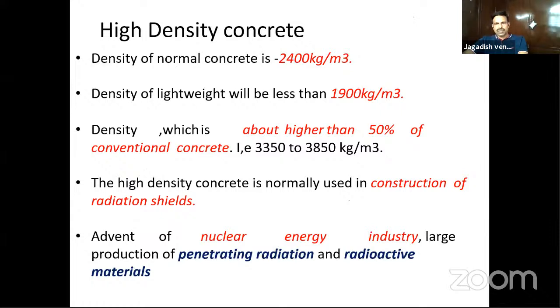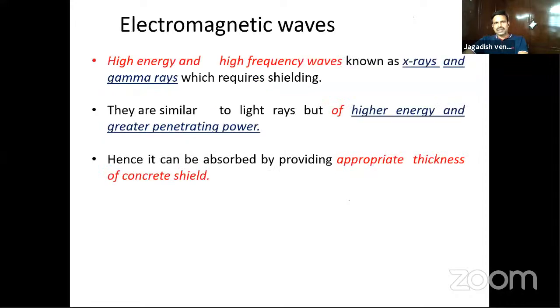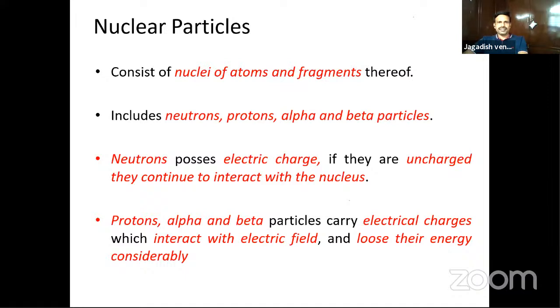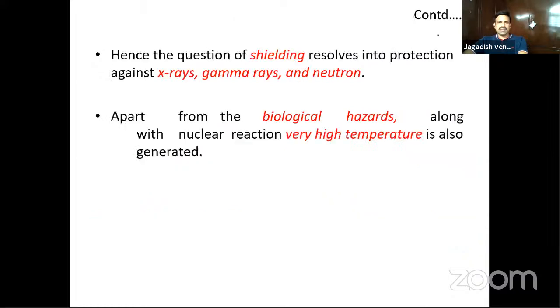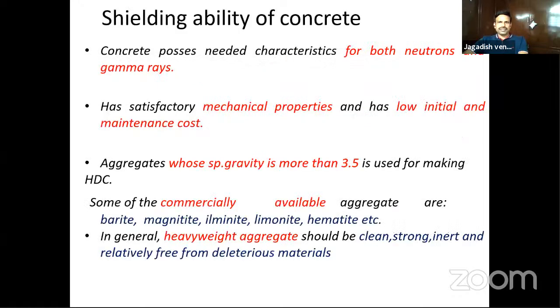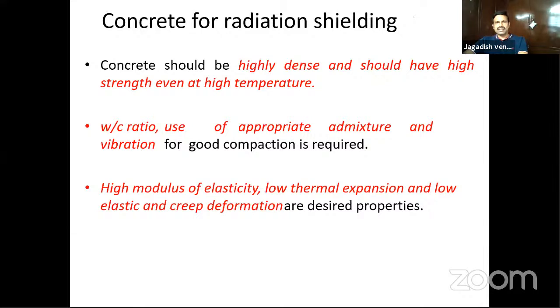High density concrete, I've already mentioned the applications, particularly the radiation shields and so on. You know that there are typical radiations, electromagnetic waves, and nuclear particles. So you should have an appropriate thickness of concrete shield to arrest these rays. And also high temperature is generated. So aggregates whose specific gravity is more than 3.5 are used particularly for high density concrete applications. Some of the aggregates are barite, magnetite, ilmenite, and so on. It should be highly dense, with appropriate admixture and vibration. For good compaction, you have to go.